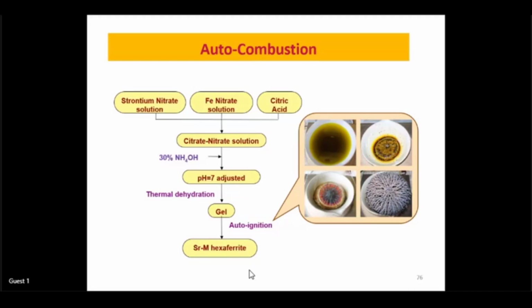So if you mix, it becomes the citrate nitrate solution, and ammonia was added, 30% weight per volume. The pH was adjusted to around 7. Then thermal dehydration forms the gel, and auto ignition starts. So the various stages are shown on the right hand side, which is part of the auto ignition.